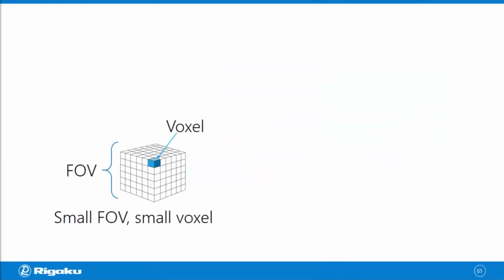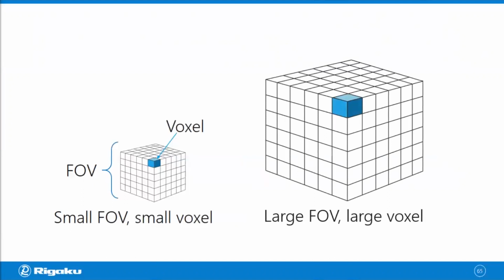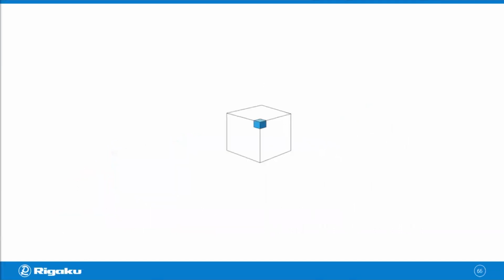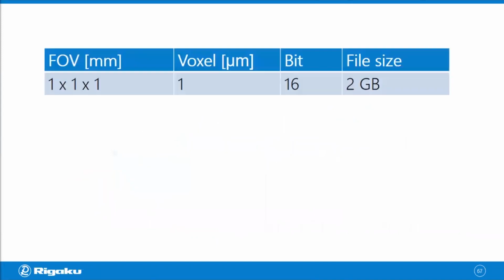And when your FOV is small, generally speaking, your voxel size is small as well. That means you have high resolution. When the FOV becomes large, your voxel size becomes large as well, meaning you have to compromise on the resolution. Sometimes people say that, well, I want to scan a large FOV, but I do not want to compromise on the resolution. Unfortunately, it doesn't work that way, and I'm going to explain why. If you have a 1 millimeter cube you want to scan, and you use 1 micron voxel size, your file size is going to be about 2 gigabytes with a 16-bit grayscale. And that's not bad at all. It's manageable. You can do analysis, whatever you want to do with it.